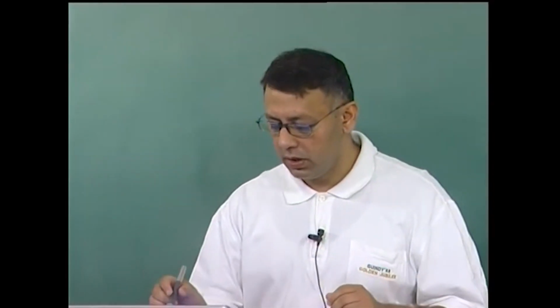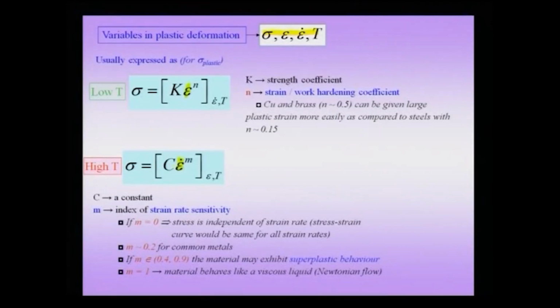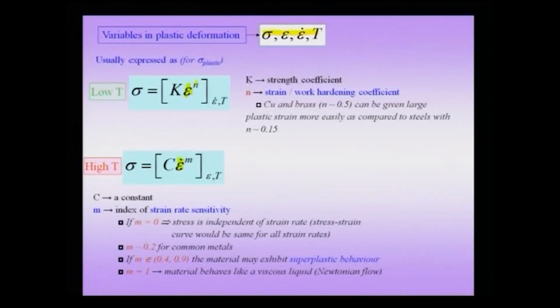At high temperatures, the microstructure continuously renews itself. That means you have recrystallization and recovery processes taking place as the deformation is progressing, and this is typically called dynamic recrystallization. Therefore, the microstructure is constantly renewing itself, and the flow stress is not increasing with progressive deformation. So, here there is strain hardening, and therefore you have an exponent known as the strain hardening exponent.